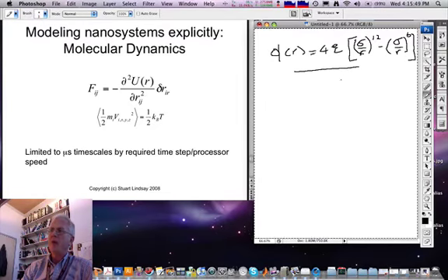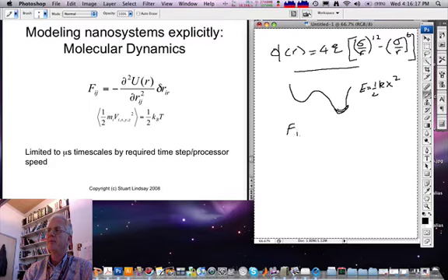The potentials don't have to be as complicated as this even, as we have discussed at several points during the current series of lectures. Most interaction potentials around their minima can be described as harmonic potentials, so that the energy looks like this, from which one can then ascribe a force constant between the ith and the jth atom as the second derivative of the potential with respect to displacement.